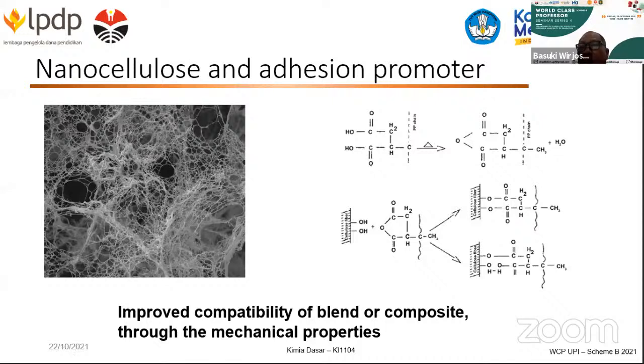They are mainly grafted with maleic or acrylic groups on the polymer. As we can see here in the chemistry, we have maleic acid groups and also maleic anhydride groups. It is very easy to understand: with cellulose fiber you can interact nicely, even chemically. They can produce a very good link between the maleic or acrylic groups and the cellulose molecules. This is the basic thing.